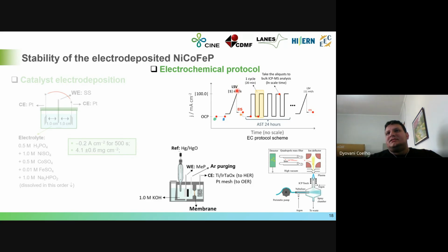So here is the LSV, the linear sweep voltammetry, used just to take the kinetic parameters from the catalyst before and after the accelerated stress test. So of course, for oxygen evolution reaction, the scanning is for more positive potentials, and for hydrogen evolution reaction is for more negative potentials. The electrochemical cell used to do this kind of experiment has two compartments, just to separate the reaction taking place in the counter electrode from the working electrode, where is my catalyst.